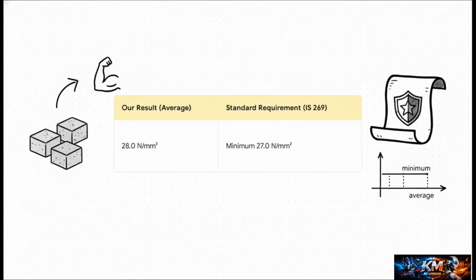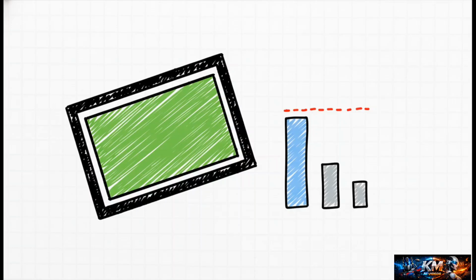So let's look at a real example for a 3-day test on a 53 grade cement. The code IS269 tells us it needs to have a strength of at least 27 newtons per square millimeter, and our average from the test, 28.0. So we're clear, we've passed the minimum. And that means the verdict is simple. It's a pass. This batch of cement does what it's supposed to do.